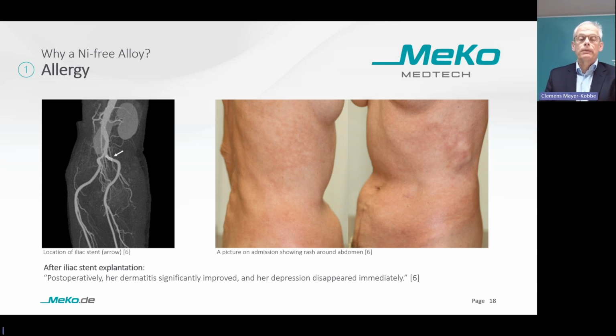Shortly after stenting, a band-like erythema was observed around her navel, which worsened over the time into a general rash around her body. Searching for the reason of the rash, finally patch test proved her strong nickel allergy. Again, no medication really helped. The only relief was the explantation of the iliac stent. After the explantation, her dermatitis significantly improved and her depression disappeared immediately.